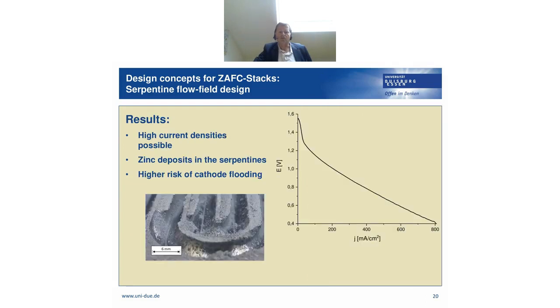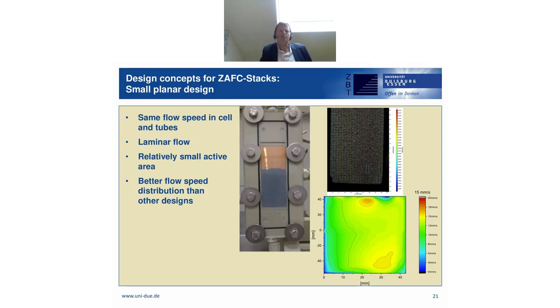So here we see a current voltage curve. We can obtain high current densities up to several hundred milliamps per square centimeter, but due to the high pumping resistance, water from the electrolyte is forced through the separator, and it leads to cathode flooding, and the water, of course, that is on the cathode side is lacking on the anode side, and this leads to zinc deposits in the serpentine, as you can see here on the picture in the bottom left. So this led us to consider different designs.